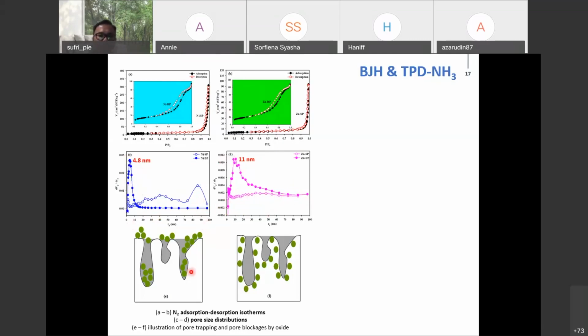In addition, this is the schematic diagram that we expect. For the doped catalyst, this looks like a pore, I assume this is a pore. There is no pore blockage, no pore plugging by the active metal, because the active metal is inserted in the crystal structure of the catalyst support, in this case the magnesium oxide.